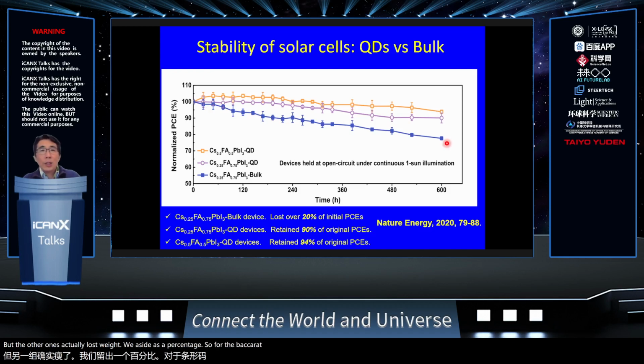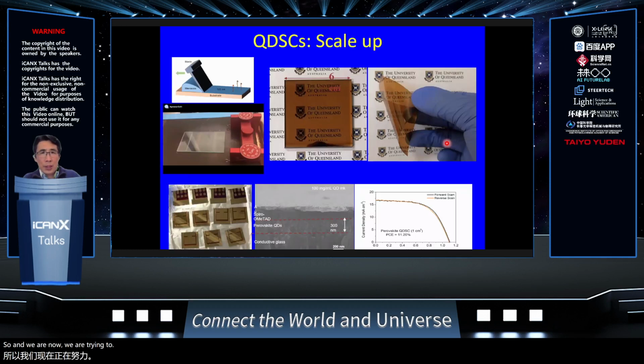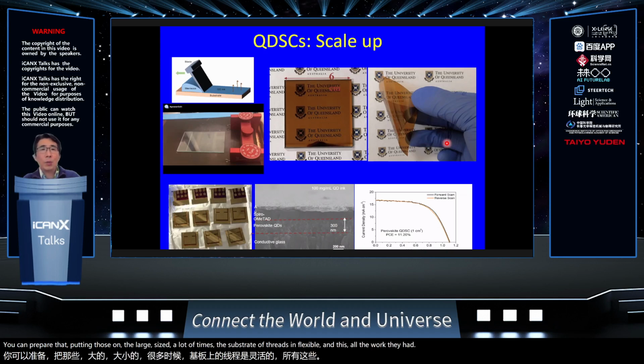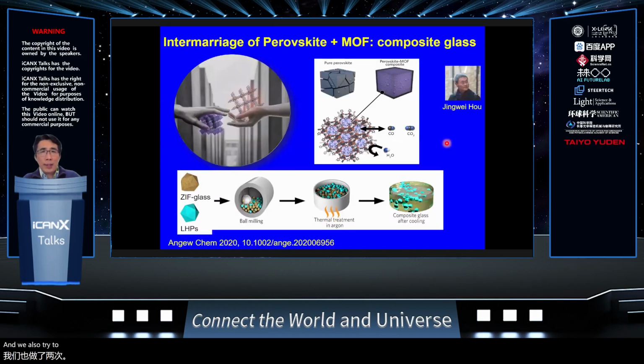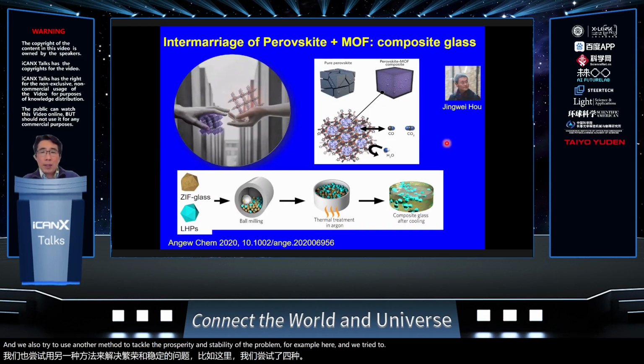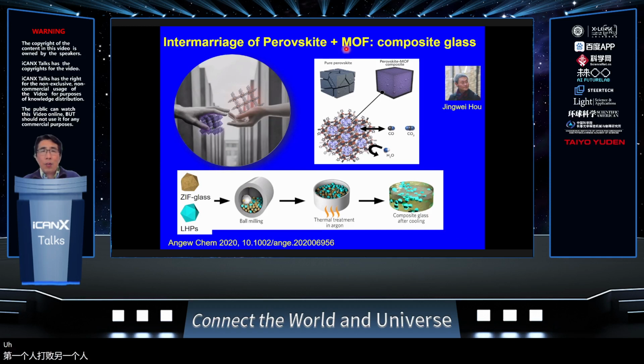So for the bulk one, we try to scale up and prepare the quantum dots onto a larger size, a larger type of substrate, and go to flexible, and this is all the work we have been doing currently. We also try to use another method to tackle the perovskite stability problem. For example, here we try to combine the perovskite with another material, a metal organic framework. This is a porous material, and we try to use a very scalable process, like this work by Dr. Jingwei Hou, using a ball milling process to put the ZIF glass and the perovskite together into the ball mill system, and then we heat this composite.